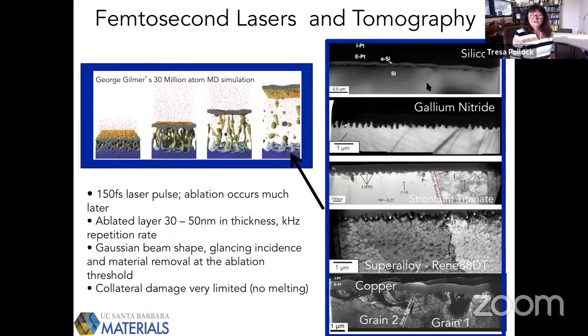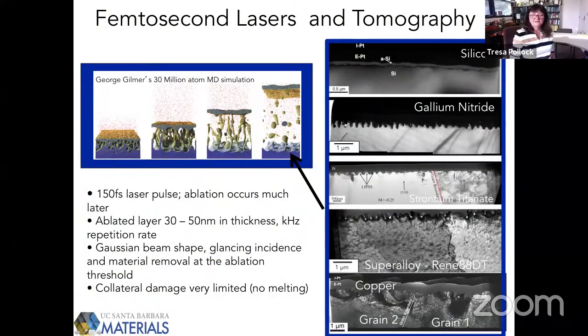And so the way that we do this is we take a sample, and with glancing incidence, we just scan the laser beam across. And in scanning the beam across, what we're doing is ablating a liquid-like layer that's about 30 to 50 nanometers in extent.